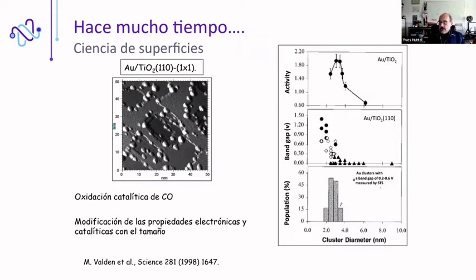Here, the difference between cluster and nanoparticle is not very clarified, but sometimes I will use clusters, sometimes I will use the term nanoparticle. But as you can see, gold that is quite inert can act as a catalyst if the size of the dimension is around 3 nanometer diameter.